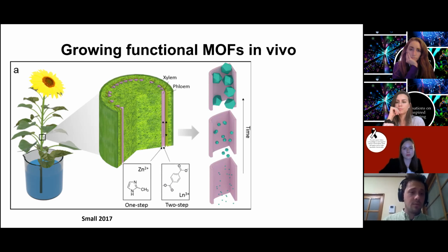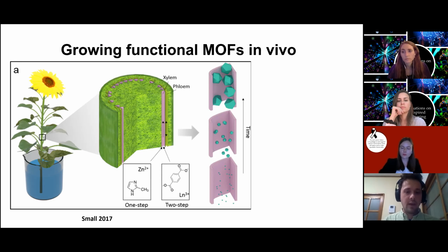And for the one step, the xylem essentially would just suck these up, and as the ingredients went up the xylem, they would start seeding and crystallizing all throughout. It wouldn't seed in the reservoir of fluid, it would only seed once it came into contact with the biomolecules. The two-step forms much, much, much quicker, which is why we had to go to two steps. And we tested infiltrating the metal first, or infiltrating the ligand first, and did some studies that I'll show you on another page.